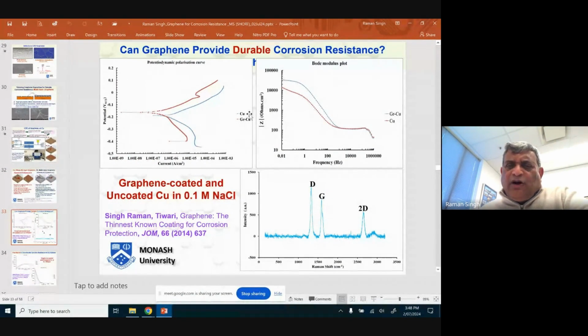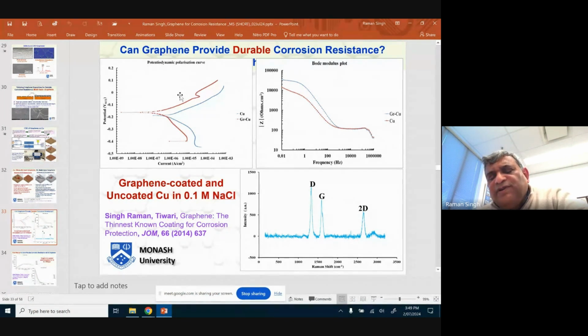We developed copper with multi-layer graphene, or two or three layers of graphene, and that graphene-coated copper gave corrosion resistance improvement of not more than 10 times or so. So we developed our own graphene, as opposed to the good quality graphene-coated copper we got from Ajay's lab. And you can see that the improvement is just by less than 10 times. It's multi-layer graphene because the G peak is taller compared to the 2D peak, but it has lots of defects.